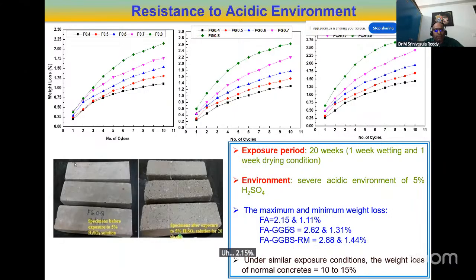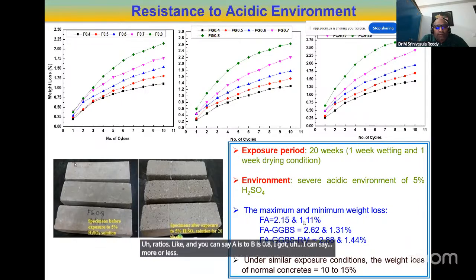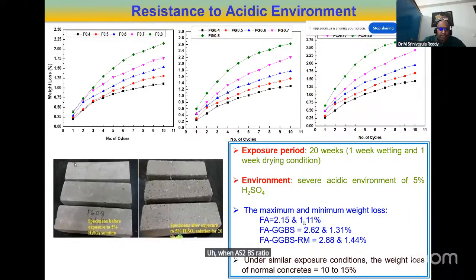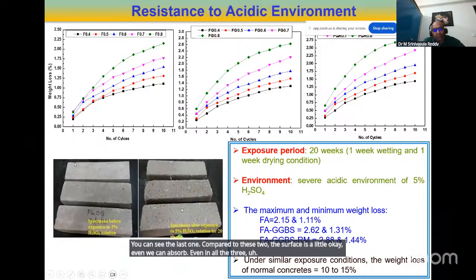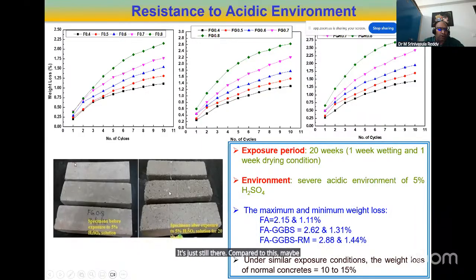2.15% is the maximum. That maximum is for the higher AS to BS ratio, like 0.8, where I got more loss. When the AS to BS ratio is 0.4, it is intact. You can see the last one compared to these two, the surface is little okay. Even in all three specimens we can observe the edges are still there. Compared to this, it is maybe little worn out because loss has taken place. But for lower ratios, 1.1% is very less.